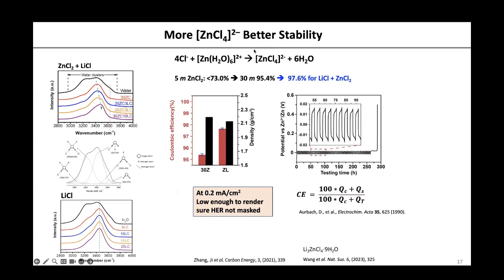So now by adding more lithium chloride, we convert more zinc cations to these complex anions. We generate more of that. And look at this. We have a blue shifted peak for water vibration. It means we strengthen water. We are strengthening water's OH bond enthalpy by adding lithium chloride, and it's producing more zinc chloro anions.